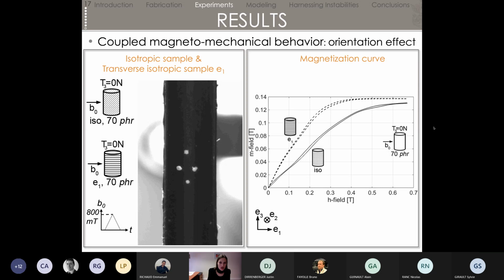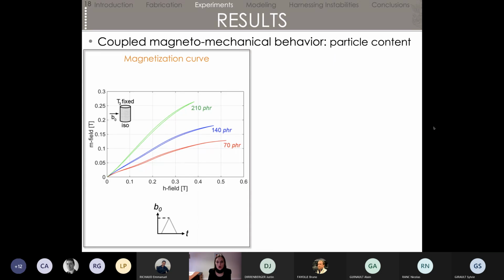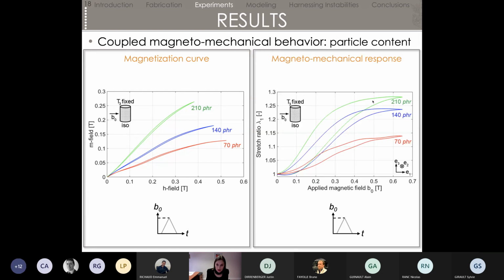What we did also was test different samples with different volume content of particles. Of course, the more particles you put, the more magnetization you get. And you can see here that the curves stop at given magnetic fields, because above these magnetic fields, if you keep applying, the whole sample will rotate in order to finally saturate.